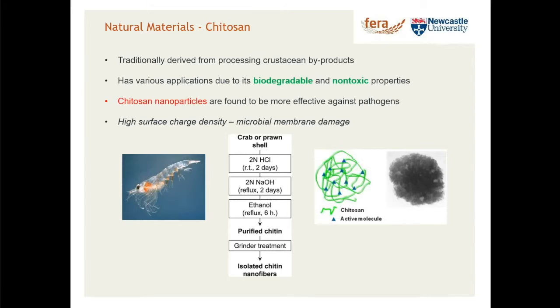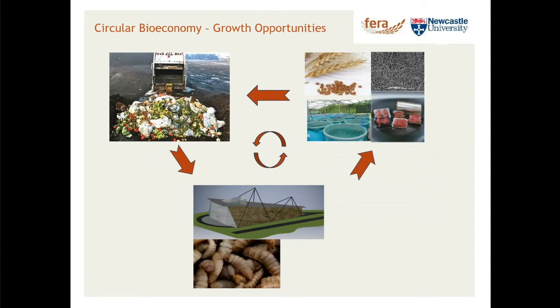But chitosan has its weaknesses. It's not so good on its own as a barrier material, but there's potential ways in which this could be exploited. So why be interested in things like chitin, chitosan, and other biomaterials? Well, certainly in the case of chitin and chitosan, we can start to see the beginnings of a very circular economy. So, for example, we can take our sort of food waste or agri-food waste, and instead of putting it into a landfill or incinerating it, what we can potentially do is feed it to things like these. These are the larvae of black soldier fly, and they'll consume pretty much anything organic and convert themselves, or use it to grow themselves into things from which we can derive protein.